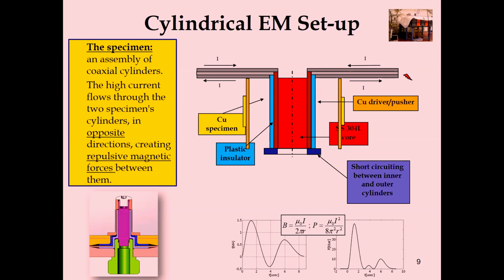So what we're using here is what's called a driver or a pusher configuration. The current is not flowing through the specimen itself. It's flowing through a conductive cylinder, which is pushing on the specimen. You could see the specimen here in yellow. And that has a very strong advantage because we're not heating up the specimen with the current flowing through it, and we could use any material even if it's not conductive, like plastics and whatever. So this would be a very interesting setup to examine any material, and it doesn't have to be conductive.